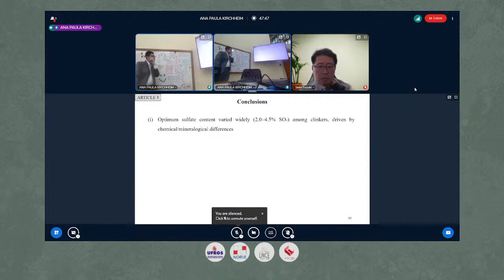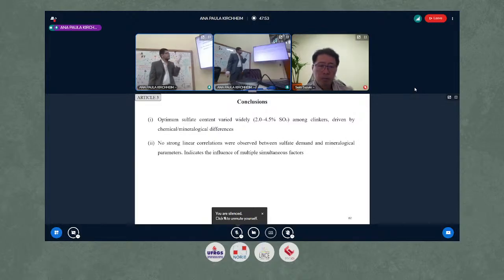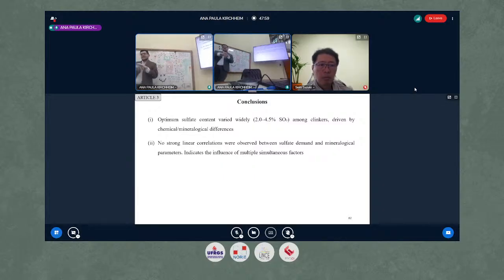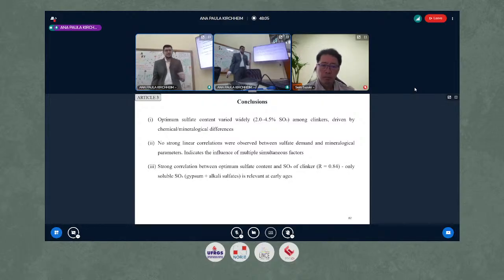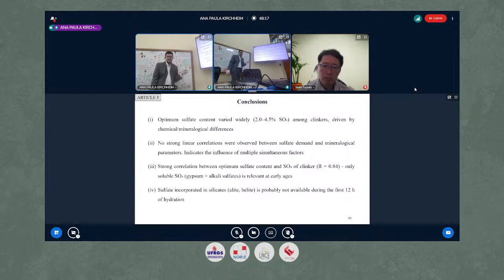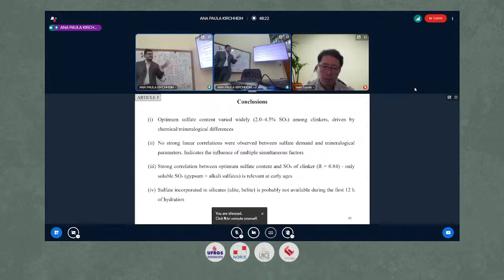So the conclusions of this study is that the optimum varies a lot between the clinkers, but there was no strong linear correlation between sulfate and mineralogical parameters, indicating that we have several different simultaneous factors. There is strong correlation between optimum sulfate and the sulfate on clinker, because not all the sulfate on clinker is soluble. We see sulfate incorporated in silicates probably doesn't participate in the first 12 hours of hydration. So we should disconsider that sulfate.